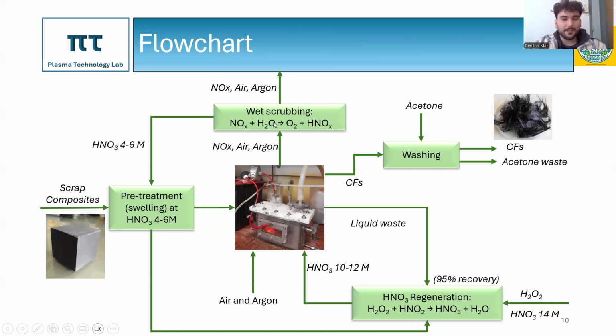From there, the larger fraction of those NOx gases is converted back to a nitric acid solution, while at the outlet of this system, we have a gas flow with a really low concentration of NOx that eventually ends up in the atmosphere. Also, the liquid waste that remains in the reactor undergoes a regeneration process where it is mixed with fresh nitric acid, hydrogen peroxide, and a solution that we recover from the wet scrubbing system.